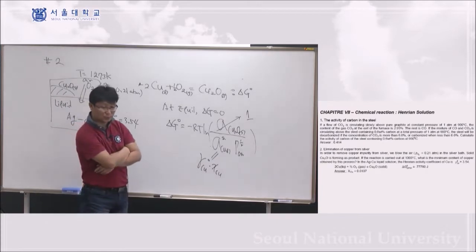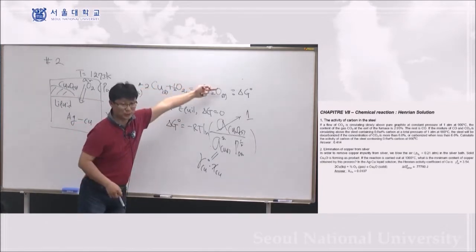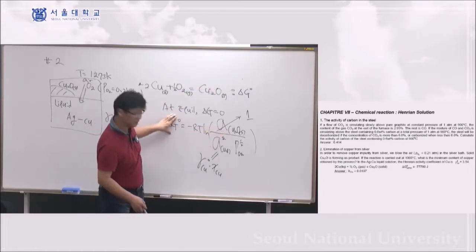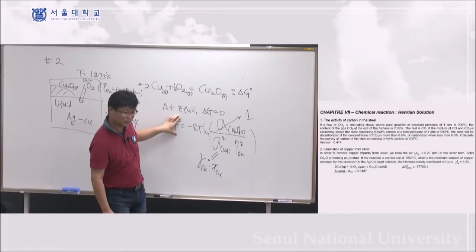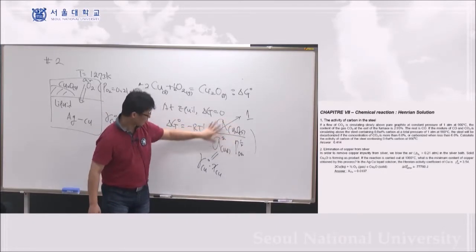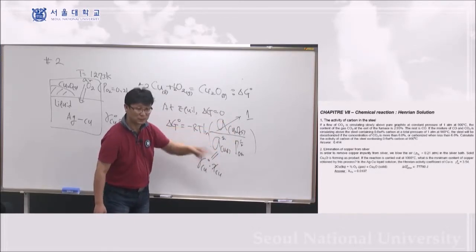Increase partial pressure of oxygen. Yeah. If you increase this, it will go more this way. So this will decrease. If you look at this, this is balanced. This is the same value. You cannot change this. So this total, the product here, is the same. If you increase this, this should decrease. Yeah. So that's one way.